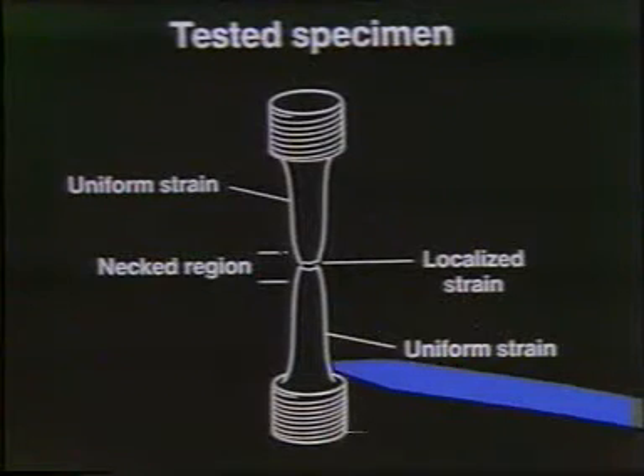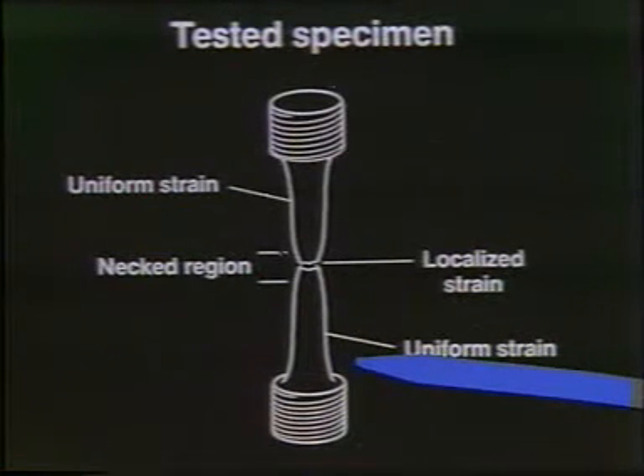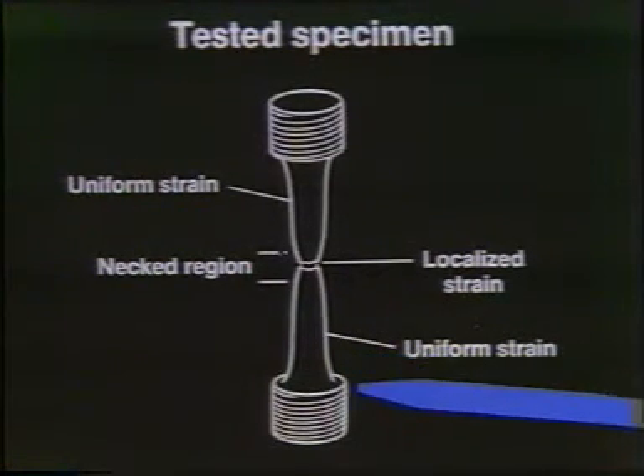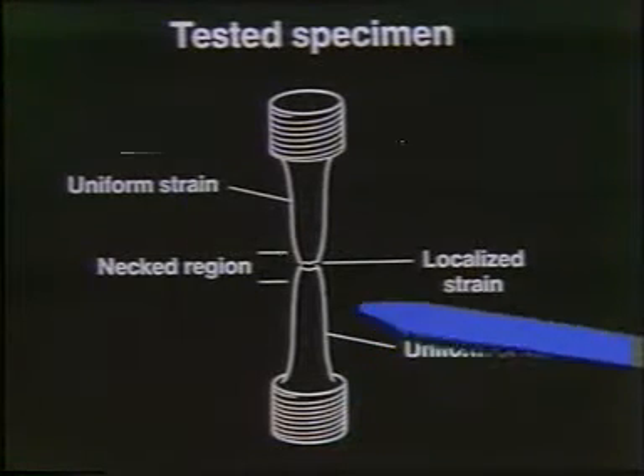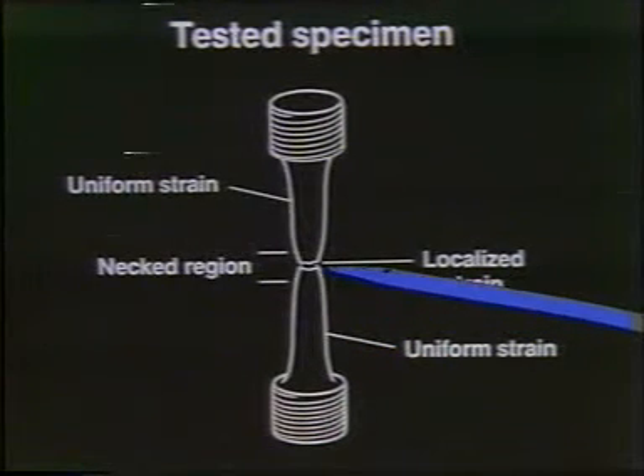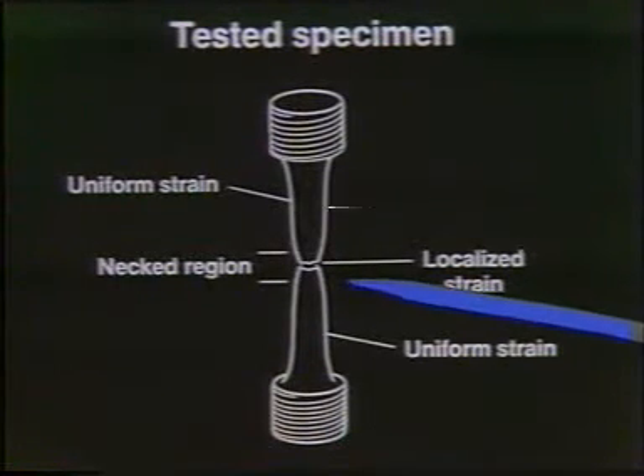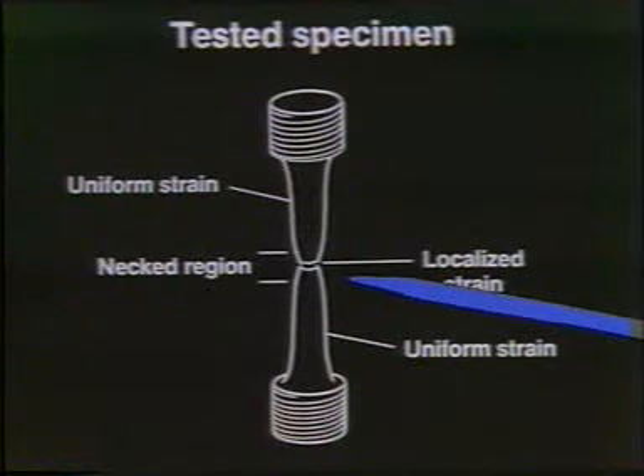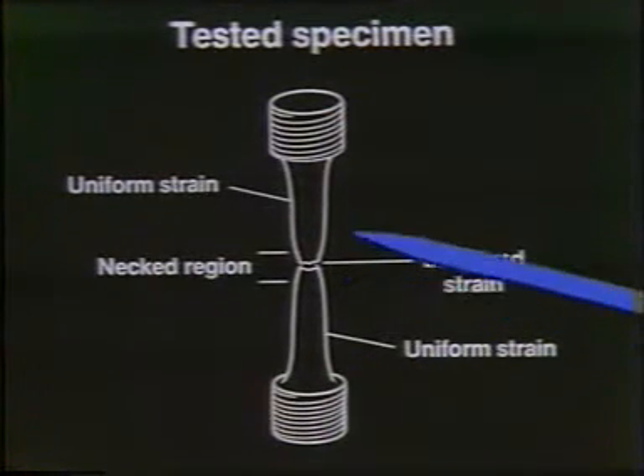But what really happens is if we have a tensile specimen, as the ones we just looked at in the last two slides, we put it in the testing machine, we pull it, and when we get to the ultimate strength, somewhere in the specimen, not necessarily in the midpoint, but we always hope it'd be in the midpoint, there will be a localized stress that is higher than the stress everywhere else around it. And so the specimen at that particular point will begin to yield or to flow faster than the rest of the material. Because we're really having flow to occur now, plastic flow.